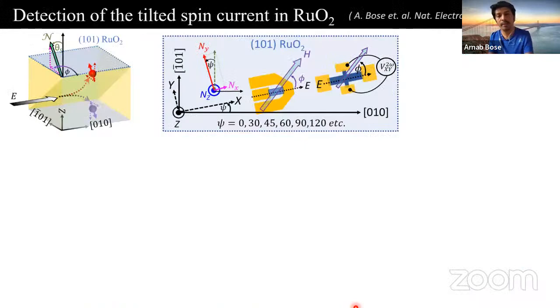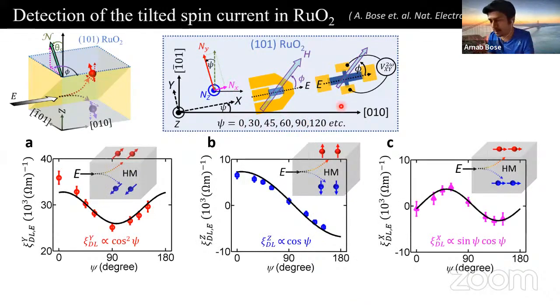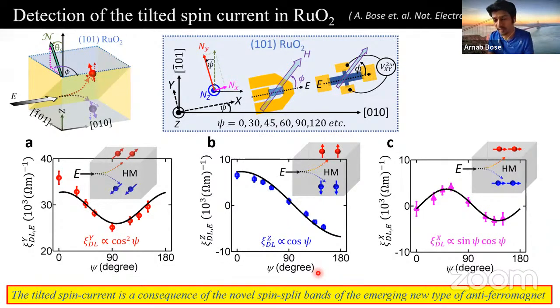So now we repeat this experiment for different crystallographic directions as shown here, and this is a summary. We find that Y-polarized spins generate damping-like torque, which follows cos square psi angular dependence, Z-polarized spins create damping-like torque, which is cos psi dependent, and X-polarized spins create damping-like torque, which is proportional to sine 2 psi. So this is pretty much consistent with the theoretical argument, and this indeed implies that we have the tilted spin current generated by ruthenium dioxide, which is a consequence of this novel spin split bands.